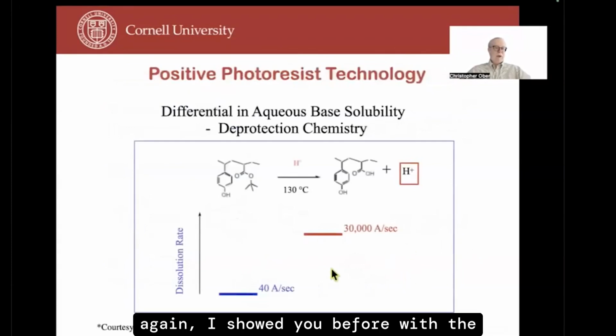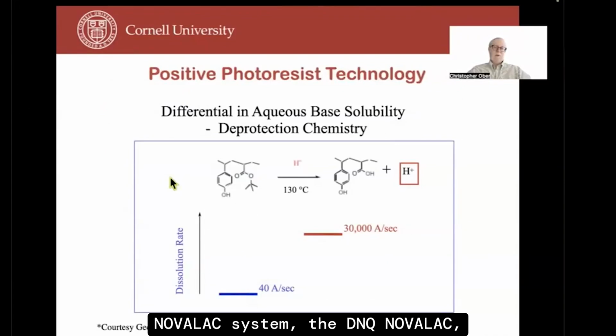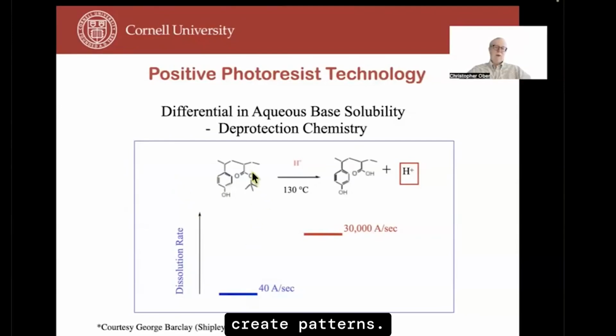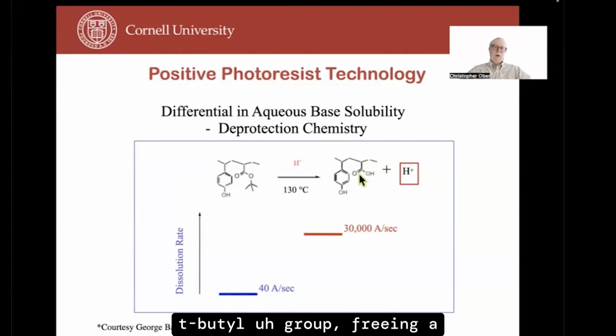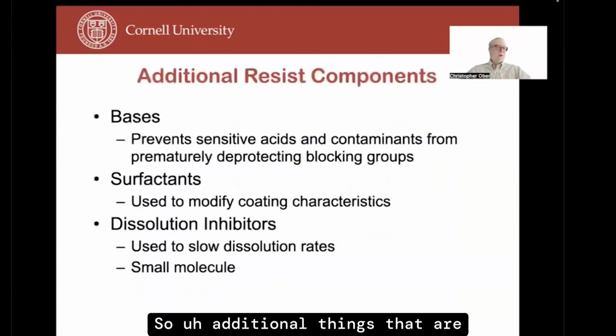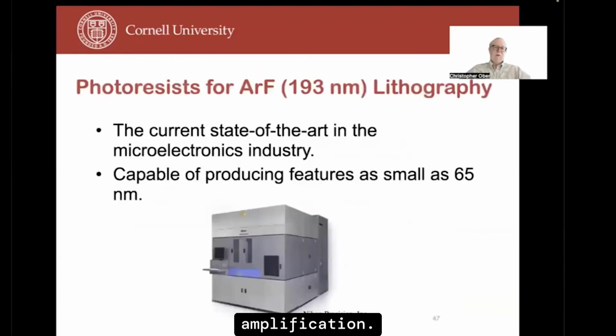So again, I showed you before with the Novolac system, the DNQ Novolac, the dissolution rate differences were important in being able to create patterns. Well, this polymer is very slow to dissolve in aqueous base. After deprotection of the T-butyl group, freeing a carboxylic acid, this is much faster to dissolve. And so we have the solubility difference that can lead to a positive tone pattern. So additional things that are thrown in a photoresist are bases, surfactants, dissolution inhibitors, all of which are used to tune performance, improve shelf life, improve deposition, but the basic concepts stay the same for chemical amplification.